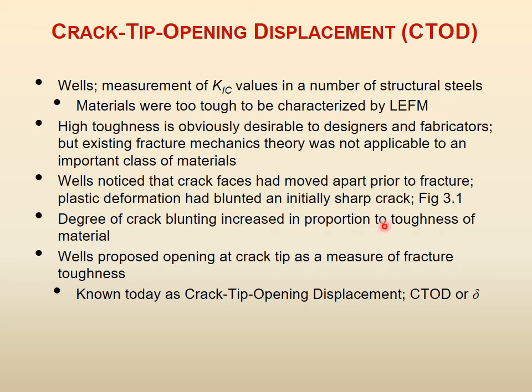If the material was more tough, then there was more blunting of the crack, more rounding of the V notch. Wells proposed opening at the crack tip as a measure of fracture toughness. This was a brilliant idea. You see, he had done a lot of work before he arrived at this. You see how there is a sharp crack, now it is blunted, it is becoming round.